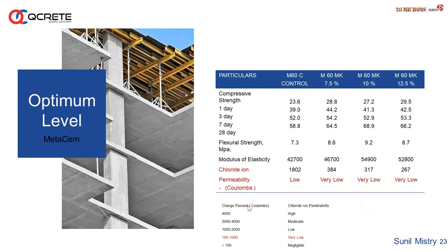the 28 day strength of control concrete is 58.8, whereas with the 7.5% replacement, the strength achieved is 64.5, and you can see here on the 12.5% replacement, the strength is reduced compared to the 10% replacement, 68.9. So as far as strength is concerned, we can conclude that 7 to 10%, 8 to 10% rather, is the ideal dose to get good, consistent compressive strength.